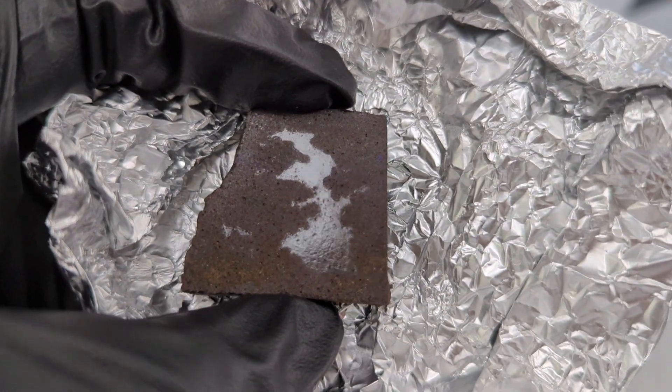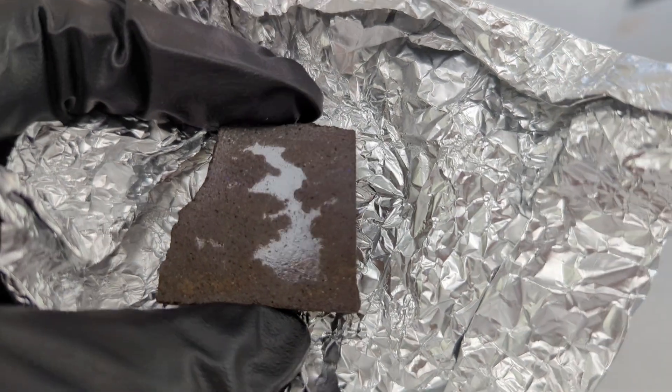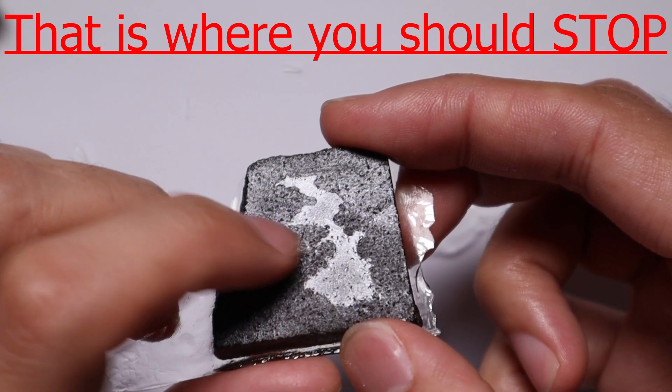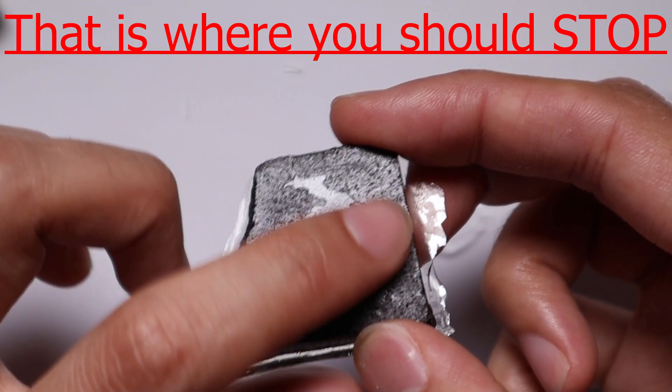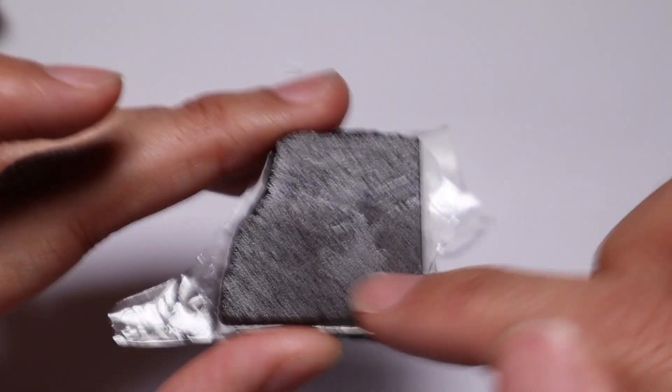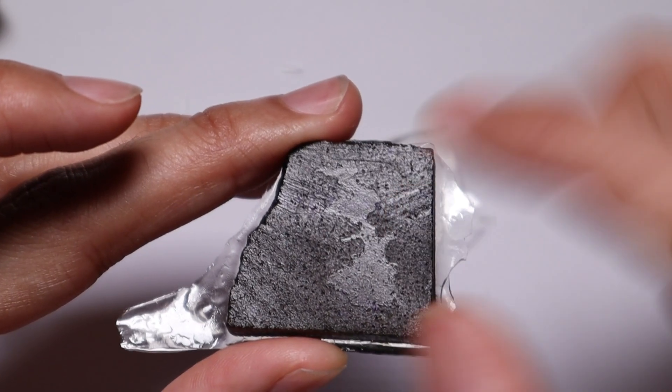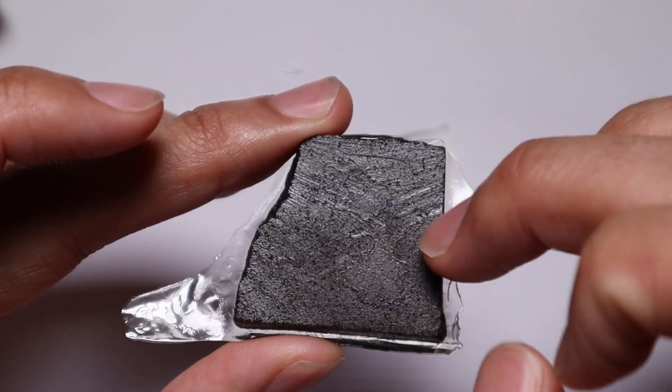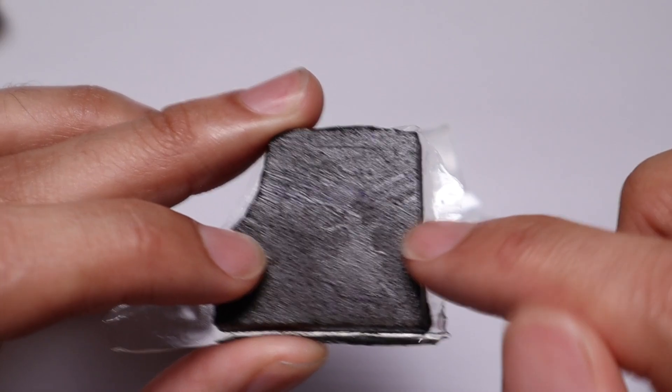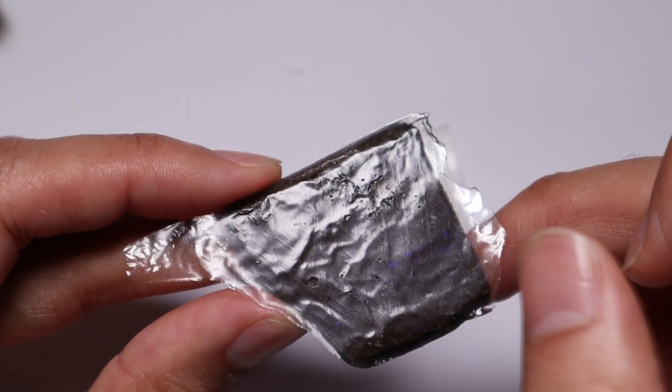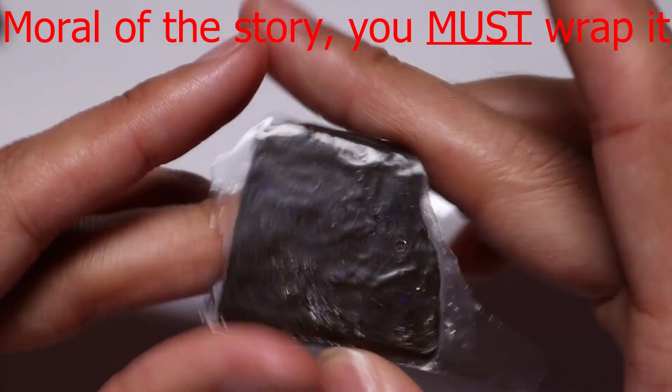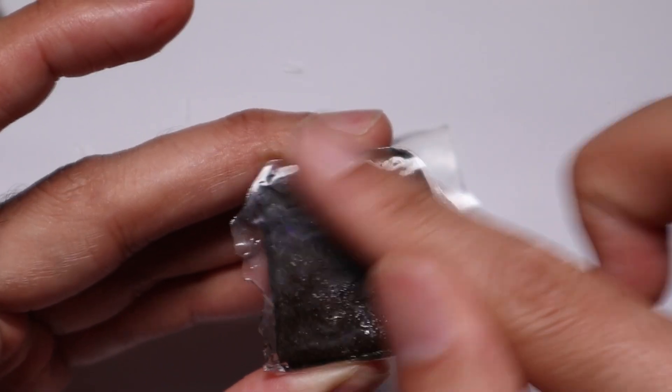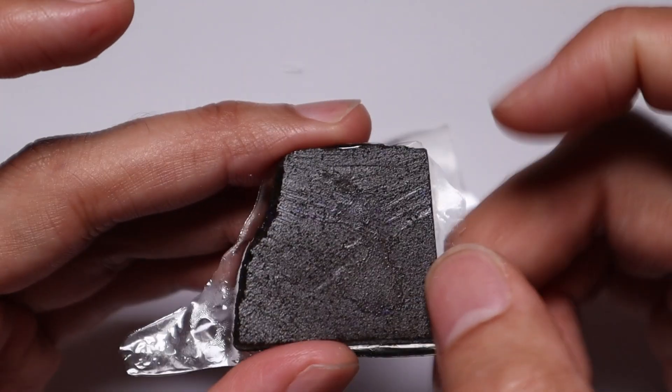So essentially after I took it out of the foil, it looked a bit more like this, a little bit matte. It certainly got in there. It's certainly solidified. This little glossy part here is what you can see in the picture. So you can get a nice little finish like that. And all you need to do that is to just keep wrapping it in the foil and just keep baking it until you get a thin layer across the surface. What I then tried to do is I deposited a bunch more of the liquid on the surface, chucked it back in the oven and let it bake. But because of how thin it is and how slow the initiator works, it actually had time to heat up, get a little bit thinner, travel all around the stone and come out the bottom. And then it just sat in a puddle and created a bit of a mess. It does make the stone look a lot darker. You can see the opal colour coming through, so it does work. But now I've got to go through and bring this all back to get to a reasonable finish again.